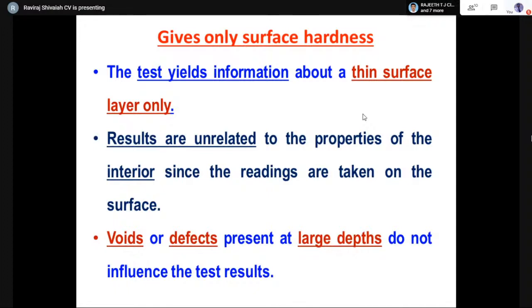So by chance, if there's a big void behind this thin surface, this particular test cannot detect that defect. Here is what you need to understand: voids or defects present at larger depths do not influence the test results. So that's a limitation of this particular test.